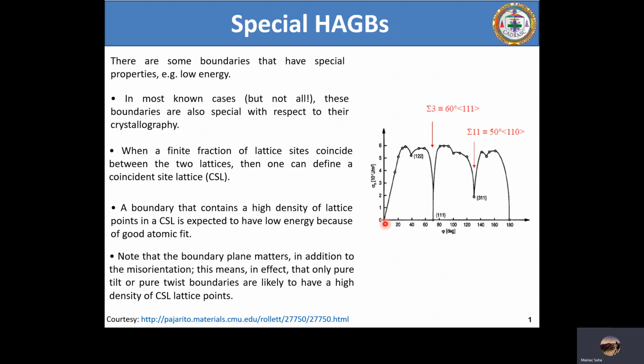These low angle boundaries in a real microstructure we see in the form of subgrain boundaries, which I also showed you in one of the previous sessions. If we consider the CSL model, we will consider these low angle boundaries, not all these local minima CSL boundaries. In the CSL model, these low angle boundaries will be considered as the sigma 1 boundary. And if we try to understand what a sigma 1 boundary means, each and every lattice plane between the two adjoining grains will be in perfect coincidence, in other words continuous with each other across the grain boundary plane, isn't it?